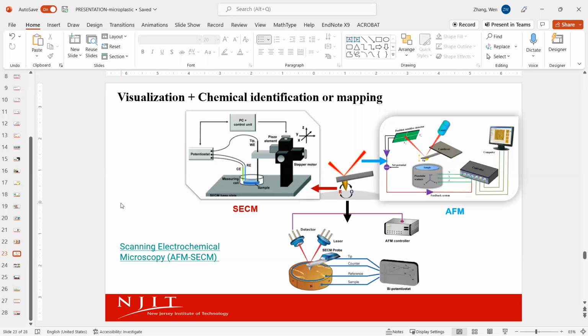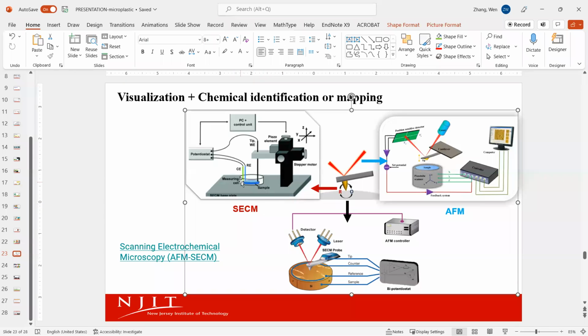So besides AFM, IR, Raman, and KPFM, this is, I would say, the fanciest technique I've ever seen. It is very difficult to operate, but it's very fancy and powerful. As you probably know, this is called scanning electrochemical microscopy, where you have a counter, working, and reference electrode. This is basically an electrochemistry design. You have a tip, which is a working electrode, and you scan the surface. Then you can map the tip-sample currents. Due to this tip-sample current, you can tell where the surfaces are reactive or more reactive versus the other areas.